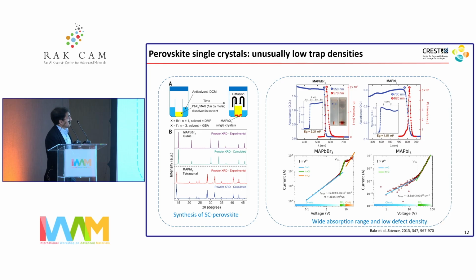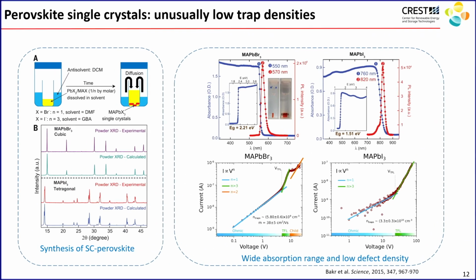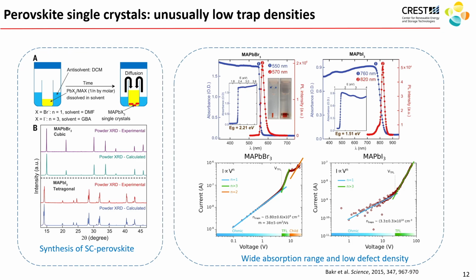And with perovskites, we could grow them into very nice big crystals that have very low defect densities, despite using very dirty chemistry and growing them in lab conditions where normally we wouldn't expect high purity semiconductors.